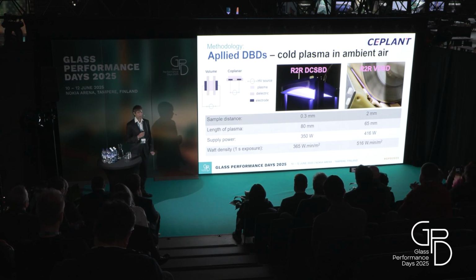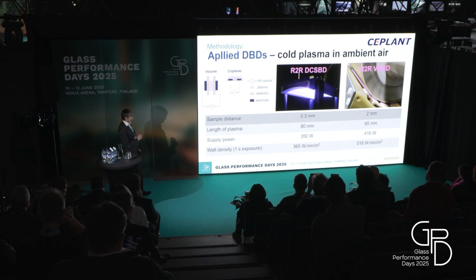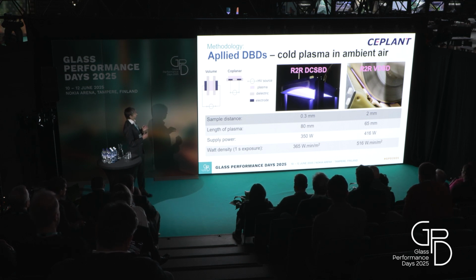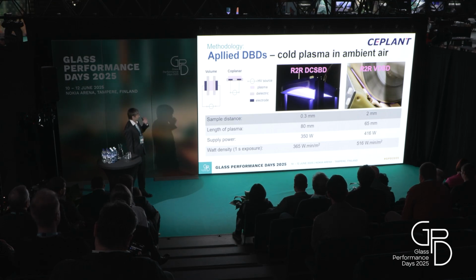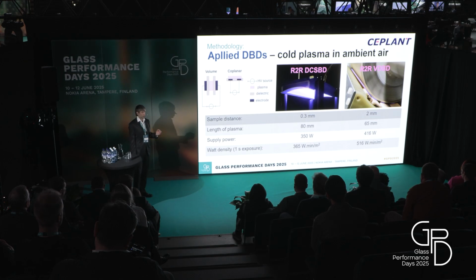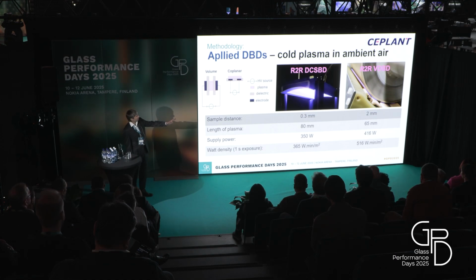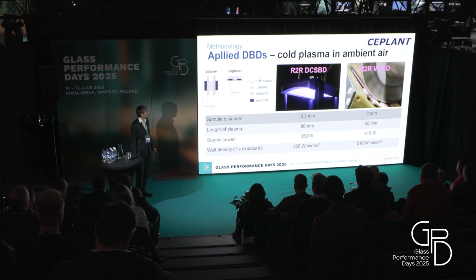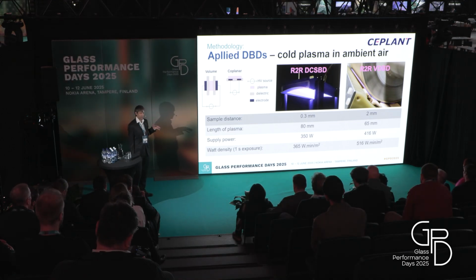The plasma sources we used are non-thermal plasma sources, because their discharge is isolated with a dielectric barrier or isolation material. We used a very thin ceramic, and then the current in this discharge is low, and also the temperature is low. Therefore, it's suitable for treatment of very temperature-sensitive materials like foils. The plasma source on the right side is directly used in industry for treatment of foils. On the left side, you can see a plasma source which was developed in Bratislava, and we also work with it in Brno, at Masaryk University, and it's called DCSBD. You see the configuration is in a curved arrangement, because we want to implement it in a roll-to-roll system which can unwind and wind, for example, flexible glass.